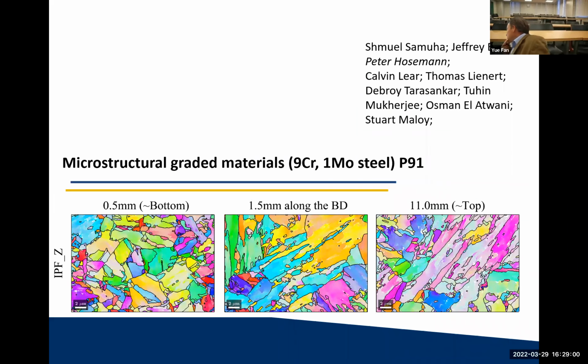Okay, second example on 3D printing is also a gradient, but in this instance, it's a structural gradient. We look at P91 or T91 ferritic martensitic steel. And when you build something, you have a bottom part, a middle part, and a top part, you build layer by layer, as we showed earlier in this cartoon.